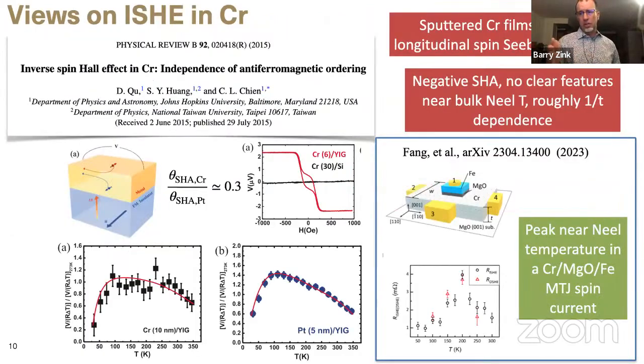And it turns out that's been looked at a little bit too. I'm giving the example of chromium because that's what I'm going to talk about here in a minute. So this is an experiment on the left, the first experiment I was aware of anyway, looking at the inverse spin Hall effect in chromium. And again, using that spin-Seebeck experiment that I just described. So there's a thermal gradient applied to a ferromagnetic YIG slab, on top of which a chromium thin film was deposited, and then you measure the voltage that's generated by that thermal gradient. And here you can see this is the signal you expect when you flip the magnetic field. The magnetization vector is reorienting in the YIG and changing the polarity of the signal. This is all exactly what you expect from the spin-Seebeck effect. The sign is opposite from platinum, which turns out to be an important thing for many experiments, and so that's what that's about.